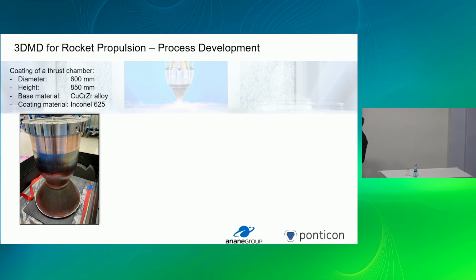If you look closely, you can see those small stripes in there. Those are cooling channels that are topped off with some metal stripes. So it's a regeneratively cooled thrust chamber, obviously, to get rid of all the heat that is coming from the inside. The base is made from copper, chrome, zirconium, and now the big challenge is to apply this jacket made from Inconel 625 in this case, which adds the required mechanical strength to the part. So the challenge is to apply nickel base Inconel 625 on top of the copper chrome zirconium material.